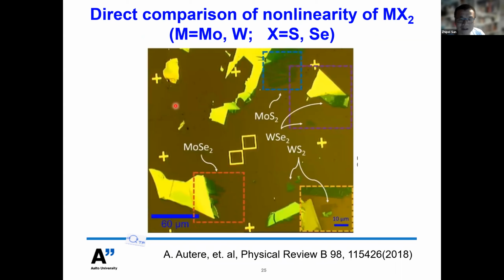To answer this very fundamental question, which 2D materials are better for nonlinear optics, we carried out a very easy but very time-consuming measurement by transferring the different 2D materials onto one substrate and then comparing them at the same time in a fair way. In this way, we don't have the problems we mentioned, for example the substrate contribution, doping, and different focus conditions.